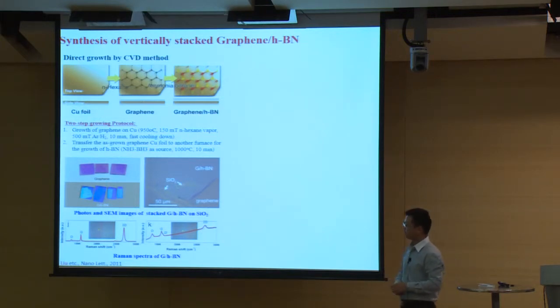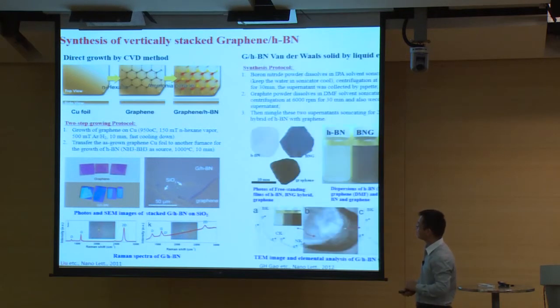So we use different technologies to determine the structure of this material. The graphene actually is monolayer graphene, and the boron nitride is on top of graphene, with a thickness of few layers of boron nitride. And the second way is we can use the liquid exfoliation method to make boron nitride atomic flakes and graphene atomic flakes. Then we simply mix them together. Because of the self-assembling process, we can get a lot of graphene boron nitride stacks from the bulk solution. So with this method, we can get controllable thickness, and we can make a large amount of materials.